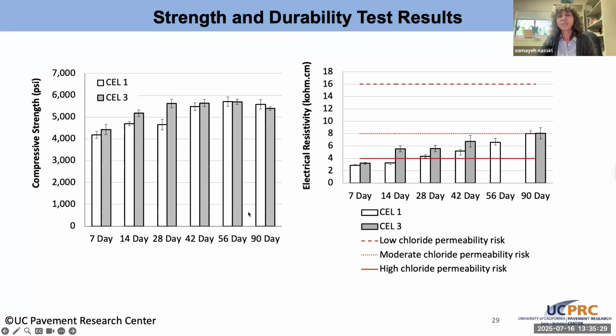Here are a couple of just examples of some of the results that are coming out now. For the first test cell, our case study here, compressive strength is showing the progression of compressive strength. Cell 3 is our test material. Cell 1 is the control. And so the measurement of all the strength coming in with time and progressing. This is electrical resistivity measured on companion specimens that were cast for both of those two test cells. And again, we see a good progression.